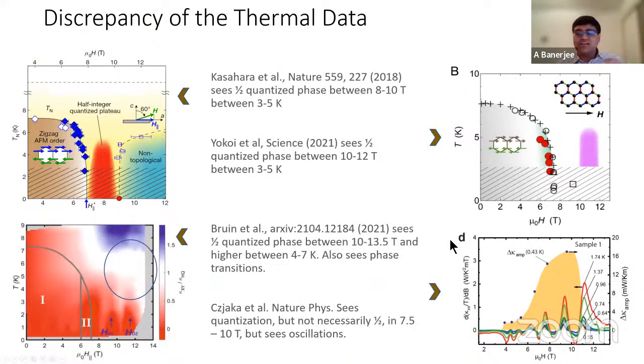So there are a lot of results out there, and there is some sample-to-sample variation which we need to be aware of. The Kasahara Nature paper showed that the thermal Hall effect happens at around 8 Tesla, while the Yokoi paper says that it happens between 11 and 12 Tesla. Then there is this Bruin arXiv paper, which I think will come out in Nature Physics sometime, which showed that it happens between 10 and 14 Tesla, quite high field.